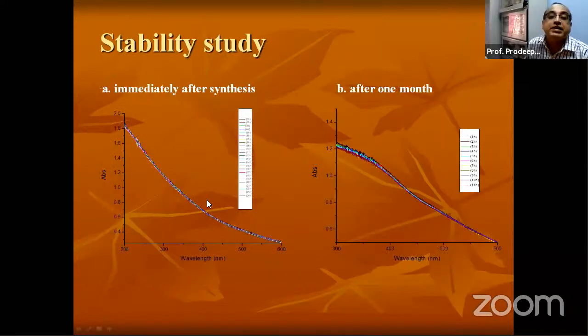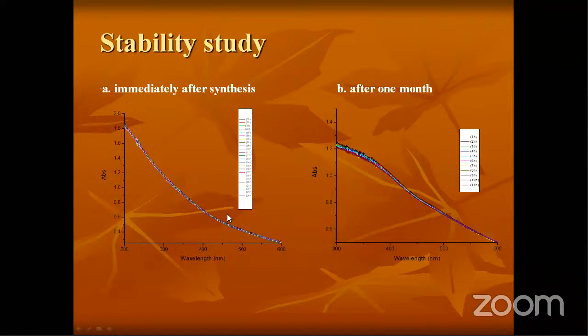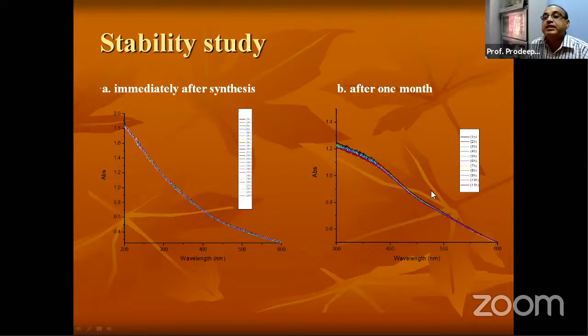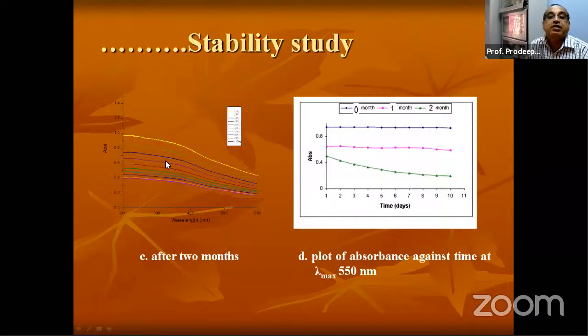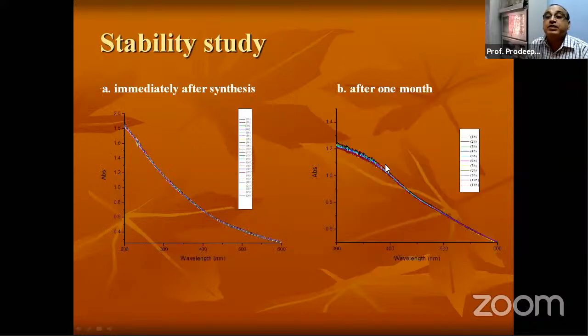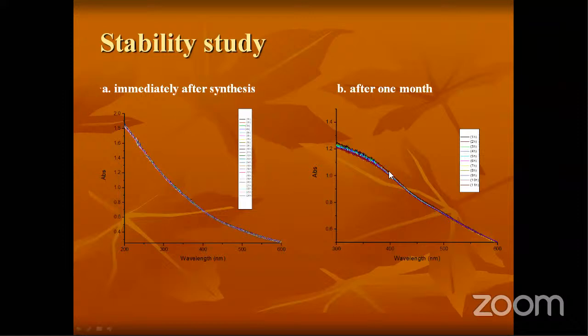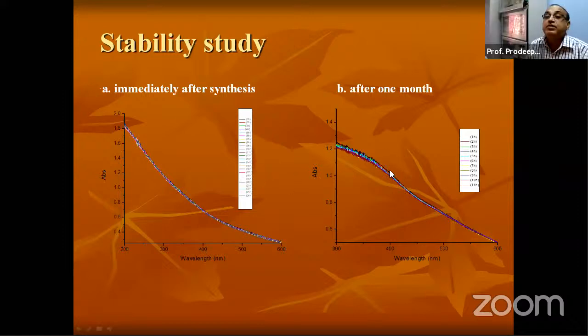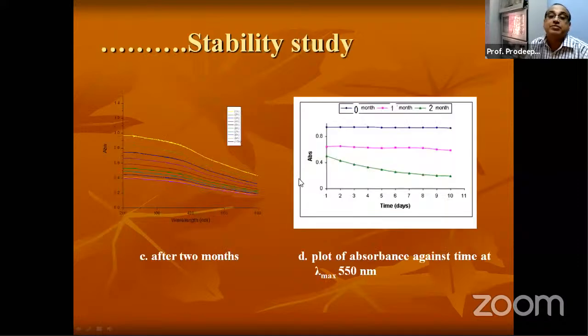Then this is a stability study. Immediately after synthesis, it's quite stable. After 1 month, slowly you can see here the stability declines, and after 2 months it declines further. Of course, this one we kept in a fridge without disturbing. So then only we could see this. Otherwise, if you keep checking after 1 or 2 days, it will definitely precipitate out. Otherwise, this dispersion stays for 1 month. And this is absorbance against time.